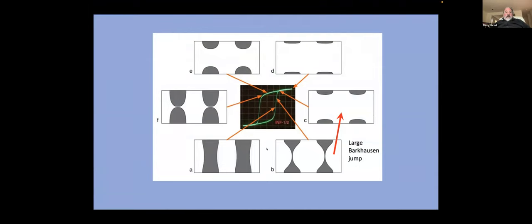So bottom left here in section A, you have a set of stripe domains. Polarization here is in and out of the plane of the screen. And this kind of configuration occupies a point about here in the BH loop. As you drive this thing through magnetization, which is one of the things you have to do in a fluxgate, you stress the domains to the point where they're going to break at this point here. And at this point, it will then jump to a different configuration of domain, which I've called channel domains, as opposed to stripe domains. But the surface expression of these two is identical. You can't actually visualize this change on the surface, but you can sure see it in the BH curves. It's this irreversible jump from this domain configuration to this domain configuration that actually creates the noise that fluxgates experience.